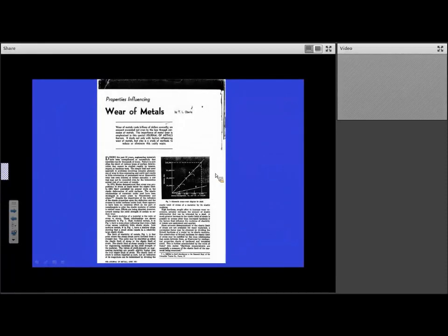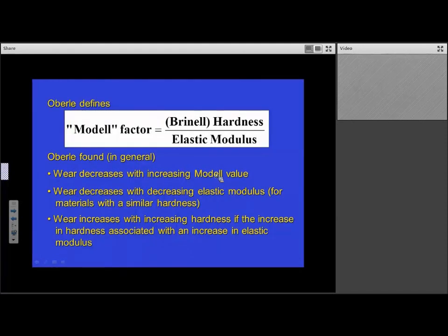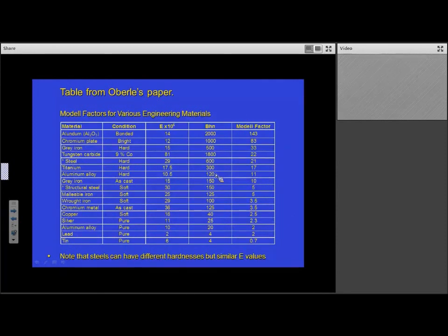This is Oberle's paper from the Journal of Metals in 1951, in which he pointed out the importance of elastic modulus. So he actually defined something that he called the Modell factor, Brinell hardness divided by elastic modulus, and he found that wear decreases with increasing Modell value, that it decreases with decreasing elastic modulus for materials with similar hardness, but it actually increases with increasing hardness if the increase in hardness is associated with an increase in elastic modulus. And he found this by doing lots of tests and then ranking materials, and this is an extract from one of his papers, where he got a better correlation between wear and Modell factor than he did between wear and hardness and wear and elastic modulus.